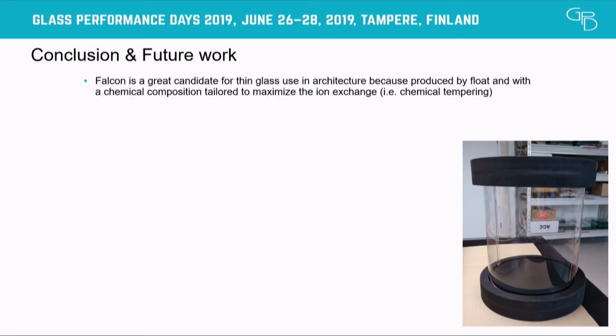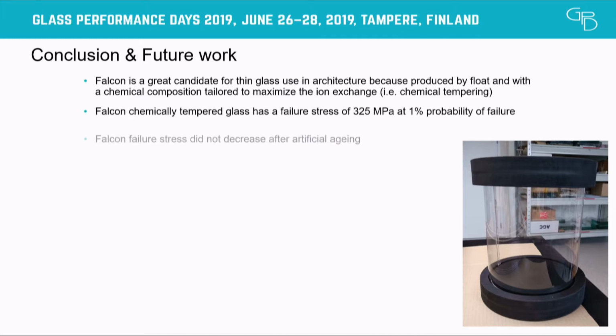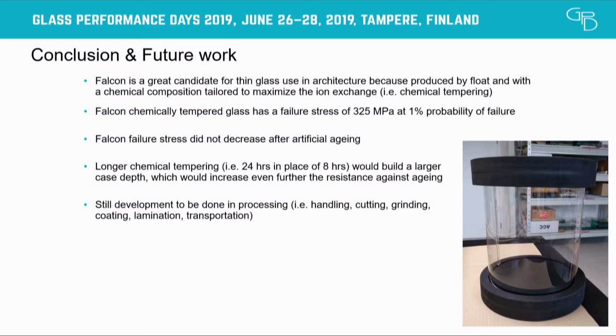So to sum up, Falcon is a great candidate for thin glass for use in architecture, because it maximizes the ion exchange due to the chemical tempering. It has a failure stress of 325 megapascals at a 1% probability of failure. We are talking about surface stress in this case. Edge stress will come in the next weeks. And the Falcon failure stress did not decrease with aging. A longer treatment will benefit in terms of case depth, and we are really working on the development.